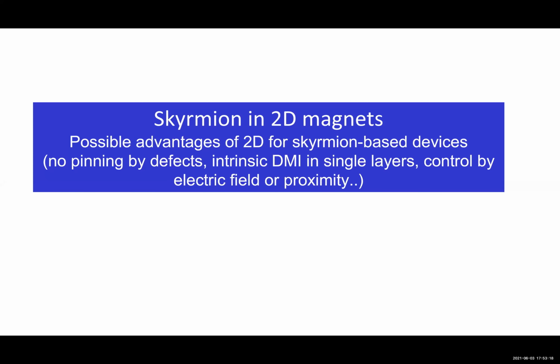But one of the difficulties is that in these 3D layers, prepared in general by sputtering, there are a lot of defects. And so the skyrmions are pinned by defects and slowed down, and the current induced motion is never very uniform.